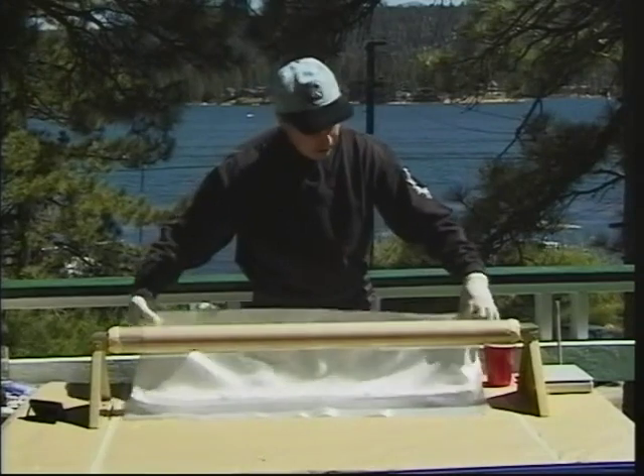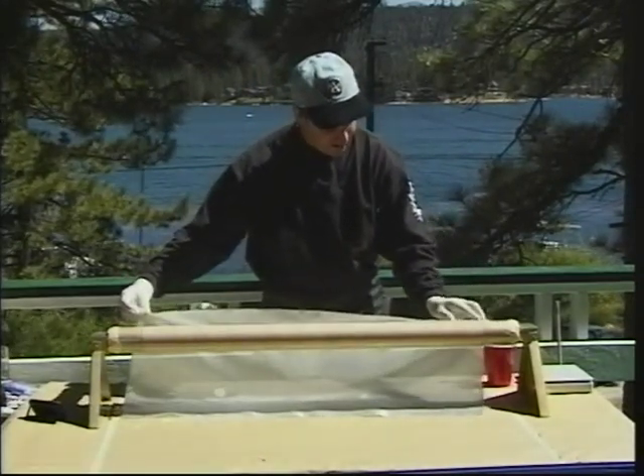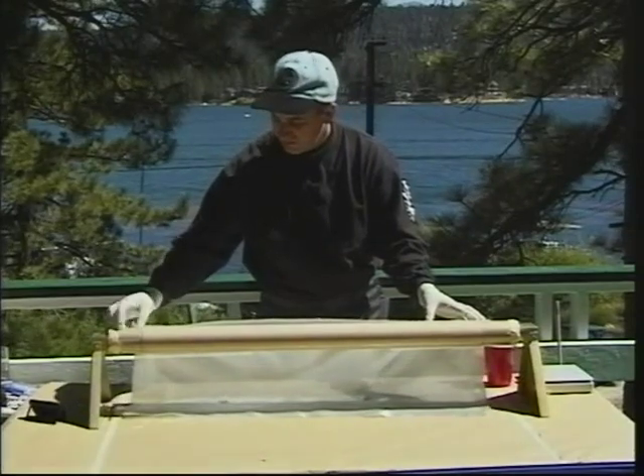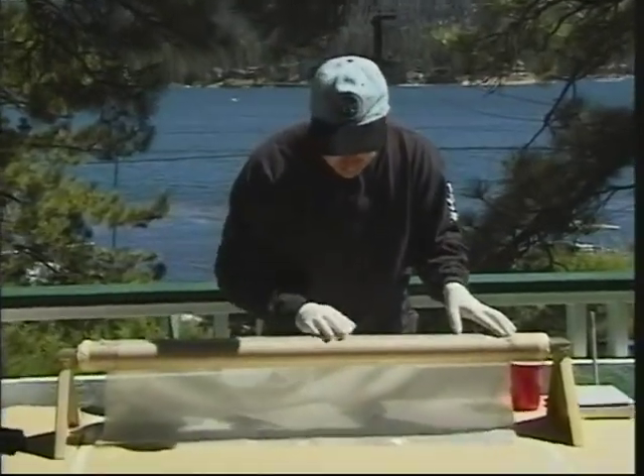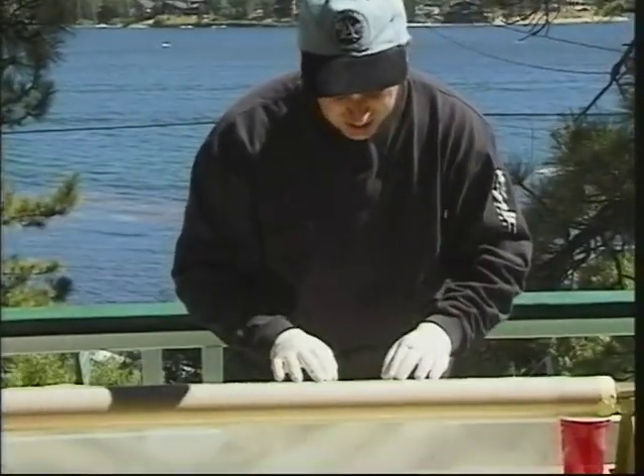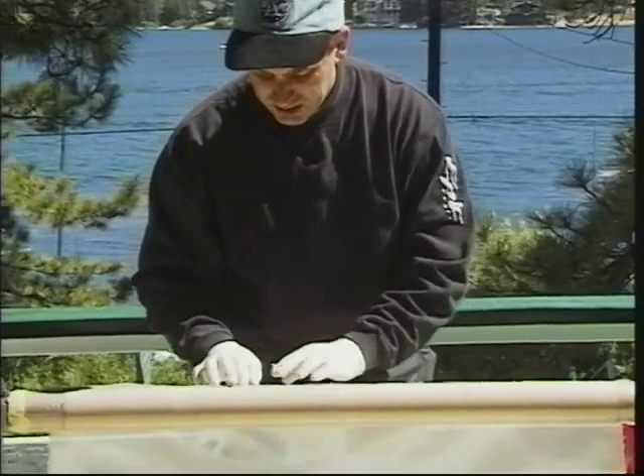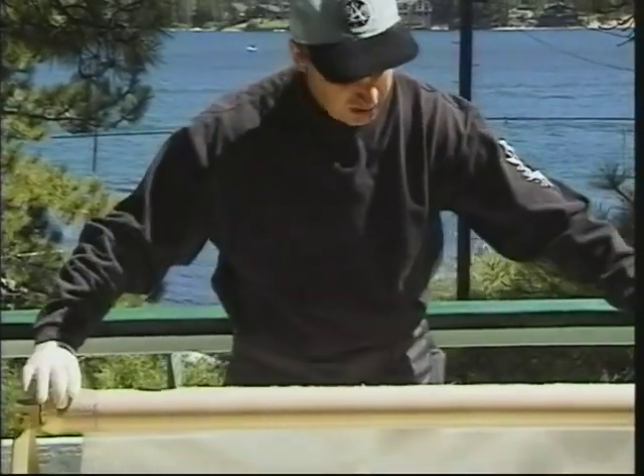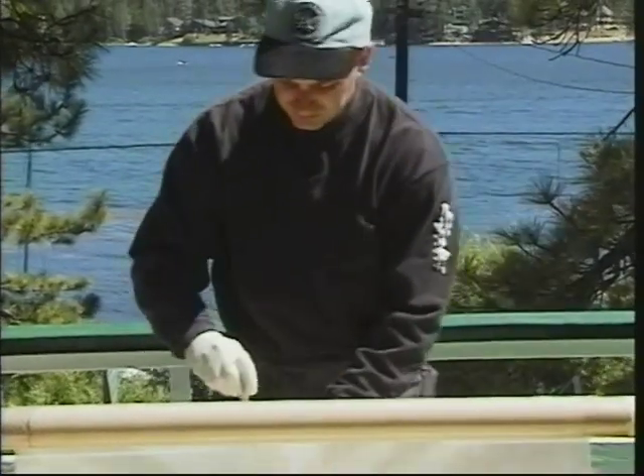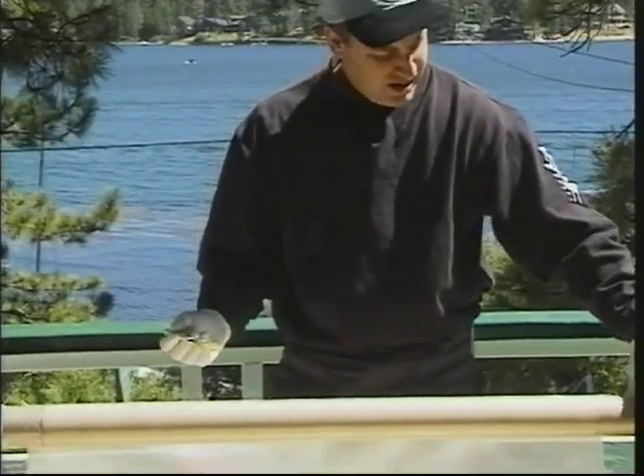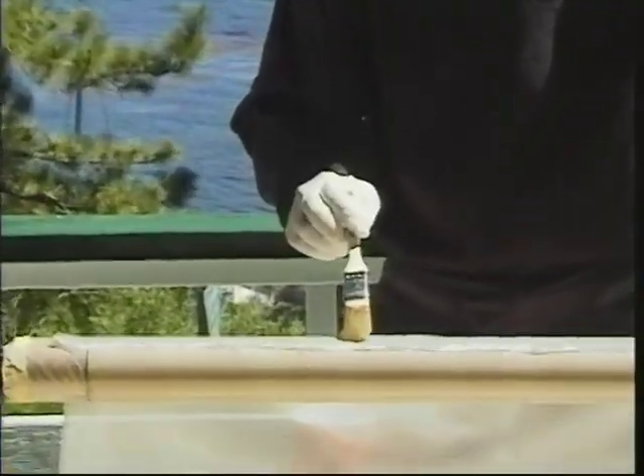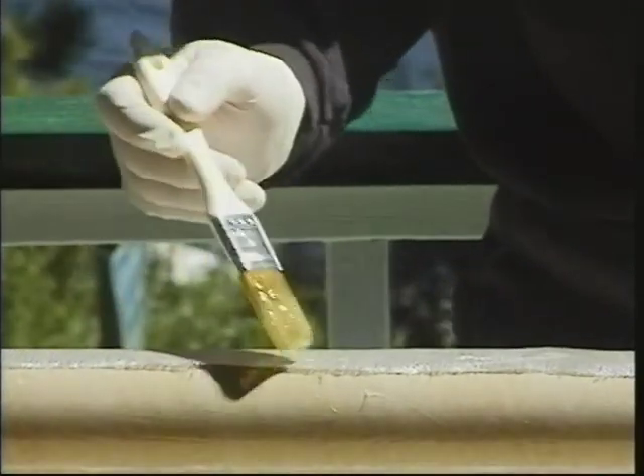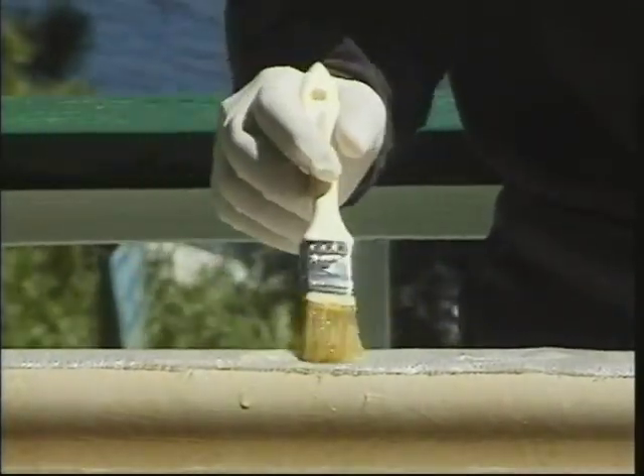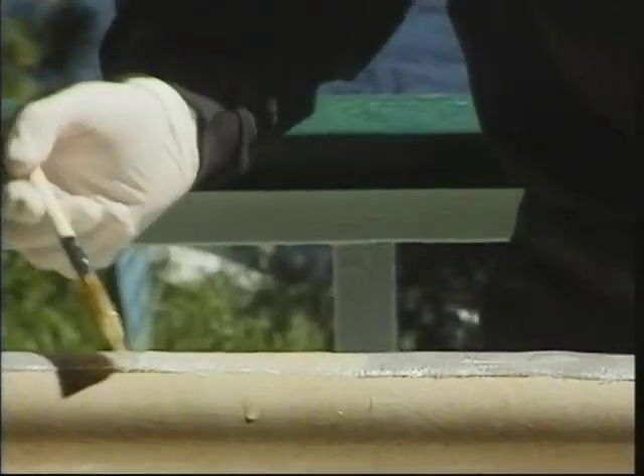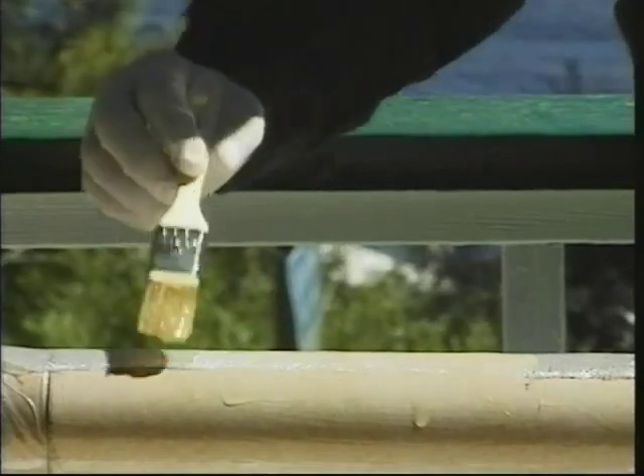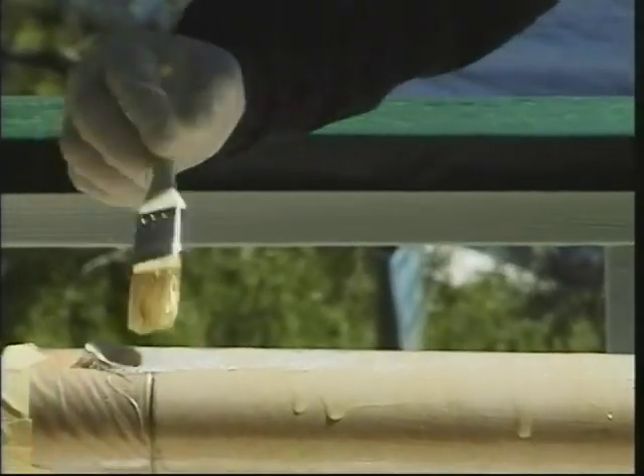And now I've got my glass cloth, and I'm just going to tack it to the tube, trying to go as straight a line as possible. It helps a lot of the time if you take and run a marker line the length of the tube. So now that's all tacked down. Now there's a little technique here, if we can zoom in on this. When you've got the edge down like this, you don't want to go brushing like crazy over it, or you'll pull up the loose fibers that are on the end of the glass cloth. So you take the brush and just roll it right over the edge like that. Rolling, and it's not picking up any of the fibers.